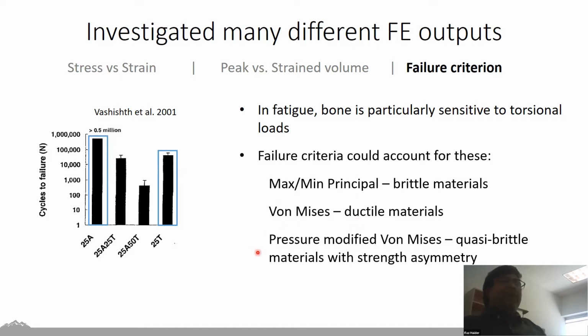The final thing we looked at is this slightly more fancy criteria called the pressure modified von Mises criteria, which in the past has been used quite successfully with all sorts of quasi-brittle materials that exhibit strength asymmetry. And specifically, I decided to use it here because in my thesis, I found it worked really well to predict the failure of the hip. Basically, what this criteria says is that the volume changing and the shape changing components of the deformation probably both relate to failure, but just in different proportion.